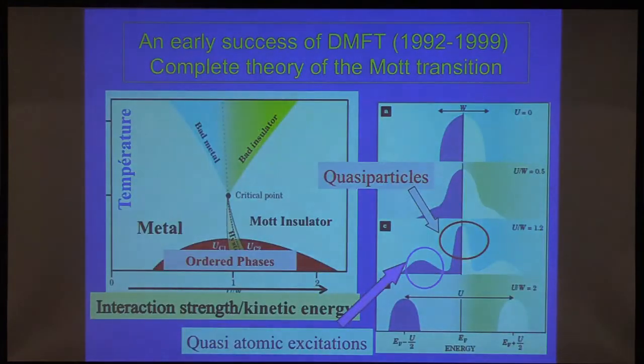One of the really nice early achievements of these methods has been to describe the transition between a metal and a Mott insulator, treating the two types of excitations in this problem on equal footing, and to provide a very detailed theory of this transition. This happened in the early 90s. Here you see the excitation spectrum. It's a cartoon, but it reflects real simulations, where you see how you evolve from a system which is just a Bloch band, this is the density of states of a Bloch band, into an excitation spectrum that has narrow bandwidth quasiparticles at low energy, plus these atomic satellites at higher energy, and at some point the system becomes an insulator, the quasiparticles disappear. So that was an early success of these approaches.